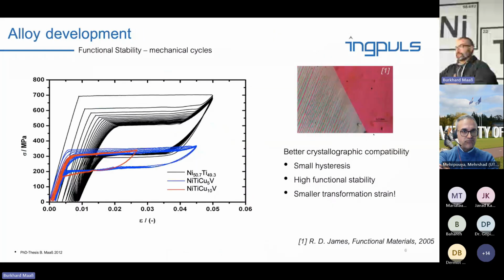Does it really work mechanically? And here you see some curves, and the answer is yes. And we can learn a few things from these curves. So we compare here a binary NiTi, nickel 50.7 alloy, with an NiTi-copper-vanadium base, 5 and 10 atom percent copper. And what do we learn? So these are all samples of 20 mechanical cycles.